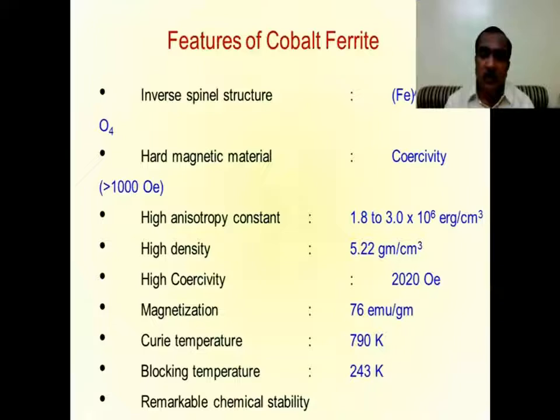The inverse spinel structure is the important characteristic of cobalt ferrite, and it is a hard magnetic material. The coercivity is more than 1000 oersted. It has a high anisotropic constant. The density is also high, about 5.22 gram per centimeter cube. It has a high coercivity of around 2020 oersted. Compared to other spinel ferrites, the magnetization is also high. It is 76, and particularly if you take the nanoparticle, then again it increases. Curie temperature is almost 800 K. Blocking temperature is also around 243 K.